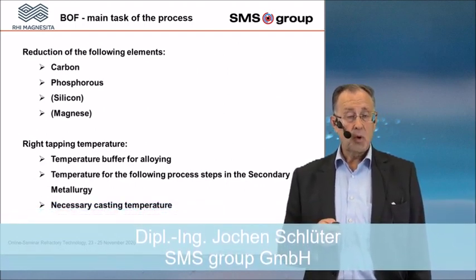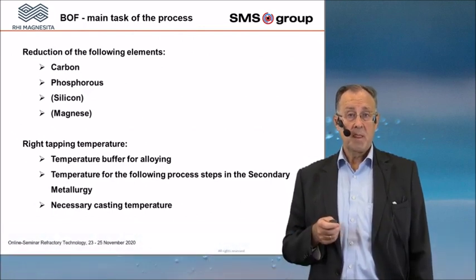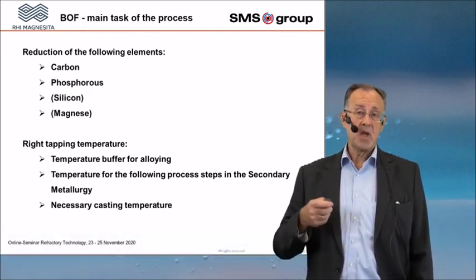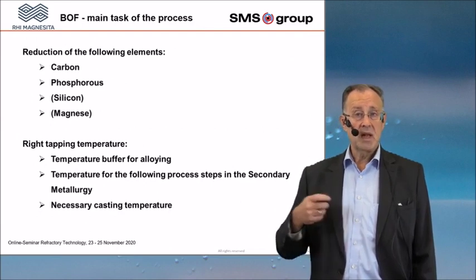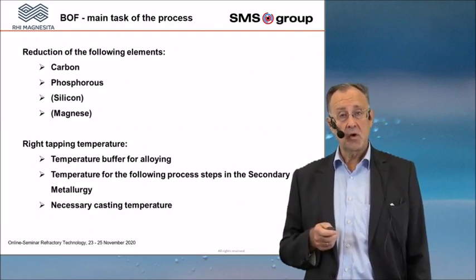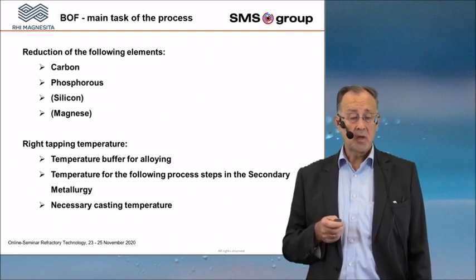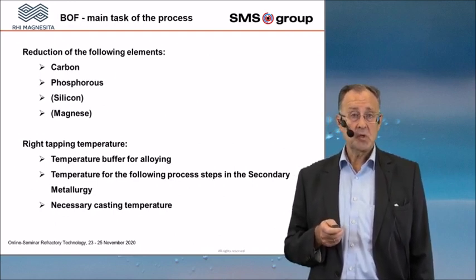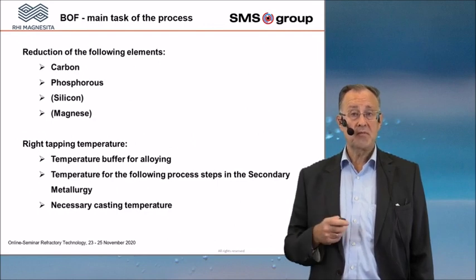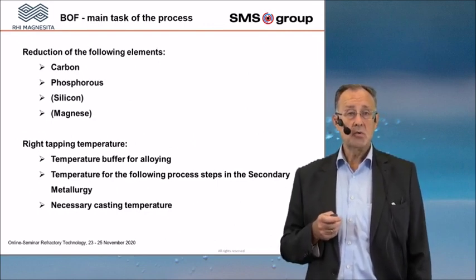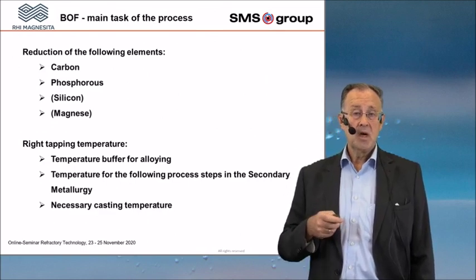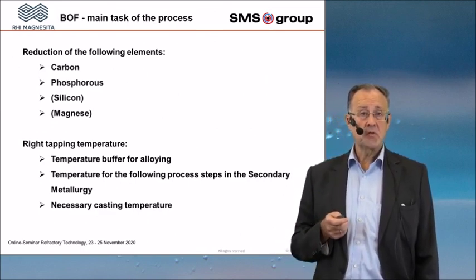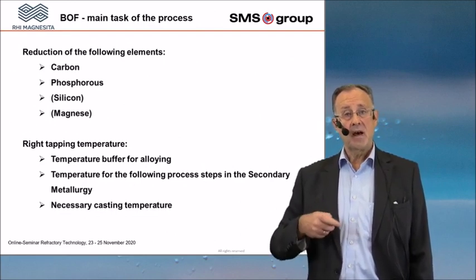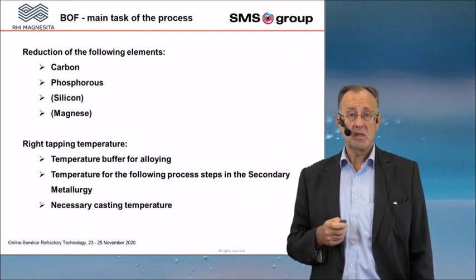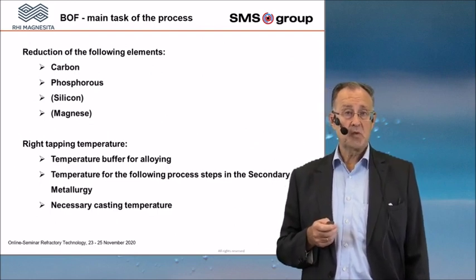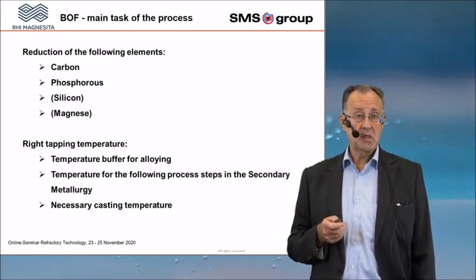The second important point is that you have to reduce the phosphorus, because phosphorus is not useful for material properties later on when you have your finished products. It is not a welcome element, so that means you have to reduce phosphorus in the BOF converter. And the problem of the phosphorus is that you can only reduce it in the BOF process, because you need an oxidation atmosphere for the dephosphorization. And later, after the tap of the BOF, there is no possibility to reduce phosphorus out of the liquid steel.